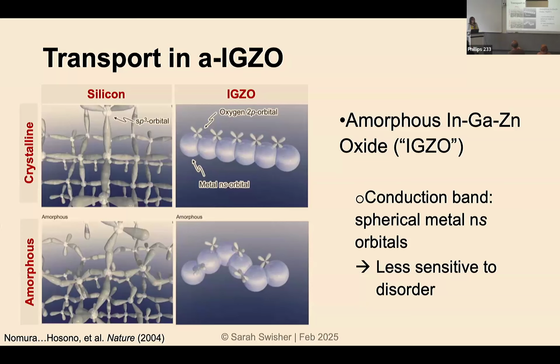So IGZO is very different because in IGZO, the conduction band is actually formed from these spherical metal s orbitals. And so with zinc oxide, you have a 4s orbital. Indium oxide, you go to a 5s orbital. So it's a bigger orbital. And what happens is that as long as you can get good orbital overlap of those spherical 5s orbitals in the indium, the disorder doesn't really hurt you that much, right? Because when you have disorder, as long as you still have overlap, you can still have good transport through the material. So it degrades the mobility a little bit, but not nearly the same way that it does with silicon.